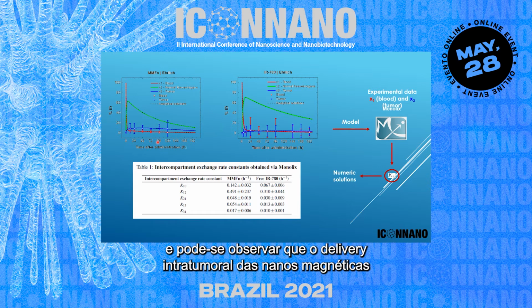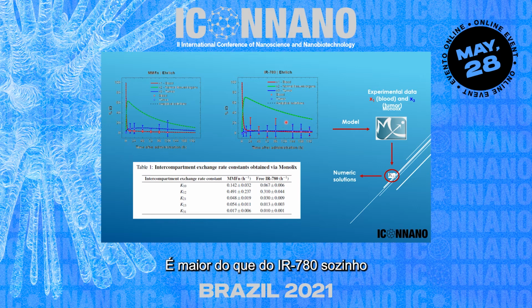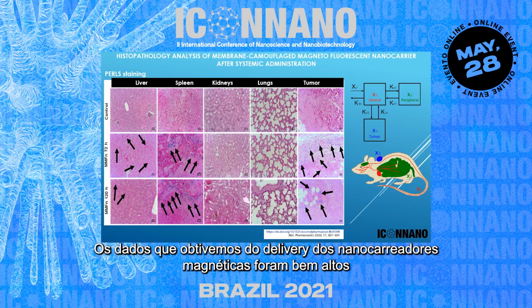And the other thing that you can observe is that the intratumoral delivery of the magnetic nanoparticle is higher than the free IR 780. So the values that we were obtaining for delivery efficiency of the magnetic nanocarriers were quite high.